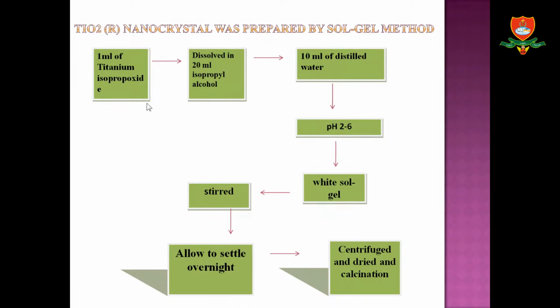First, let us see the synthesis of titanium dioxide nanocrystal by Sol-gel method. 1 ml of titanium isopropoxide is dissolved in 20 ml of isopropyl alcohol. And then the solution is transferred to a beaker containing 10 ml of distilled water. The pH is maintained between 2 to 6 by the addition of 1 molar nitric acid and 1 molar sodium hydroxide. After maintaining the pH, a white sol-gel is formed, and then the solution is allowed to vigorous stirring overnight to settle the product. After that, the solution is centrifuged to separate the solid particles and the liquid, and then it is allowed to dry. After that, it is calcinated at 300 degrees Celsius for 4 hours. Then we get fine crystals of titanium dioxide product.